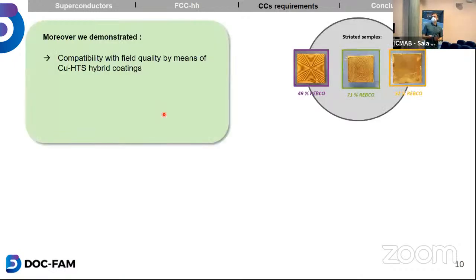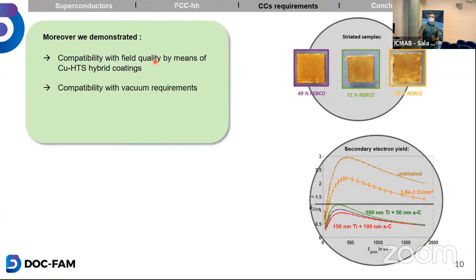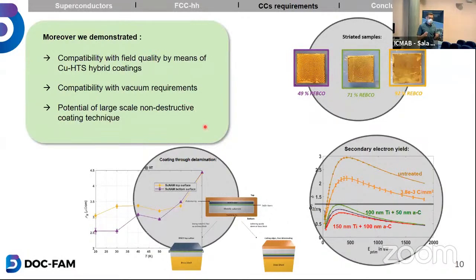During the last years, we also demonstrated other important properties, like the compatibility with the field quality in the beam screen chamber and the compatibility with the vacuum requirements. And we also found a coating technique which is potentially suitable for large-scale applications, and it's not destructive. So we are actually able to attach the coated conductor to the beam screen chamber without damaging it, which was also an important challenge to overcome.